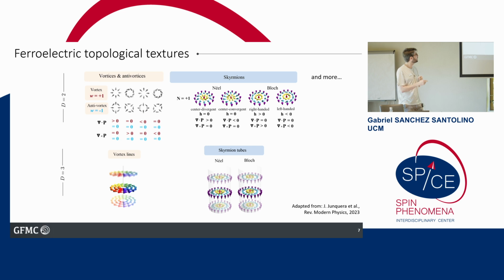I'm going to show you again the same diagram that Fernando showed yesterday from his advisor, where they calculated all the ferroelectric topological structures that were supposed to be stable. We can have vortices and anti-vortices, skyrmions, vortex lines, but these are very different from the magnetic structures. In a magnetic structure, the order parameter is the spin, and it can rotate freely, but in ferroelectric materials, the order parameter is the polarization, and it goes with the distortion of the lattice. So this is a very energy costly effect.